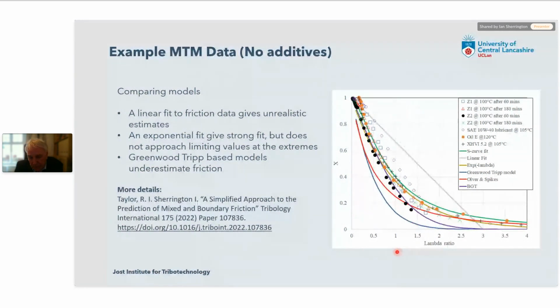If we look at a particular lambda ratio, let's take lambda ratio 1, you'll see that the amount of mixed and boundary lubrication predicted by the Greenwood Tripp model is about 90% hydrodynamic. But on our model, which remember fits the data curves, it's more like 70%. So the Greenwood Tripp model, you could argue, significantly underestimates the amount of mixed and boundary lubrication for quite a lot of this range.